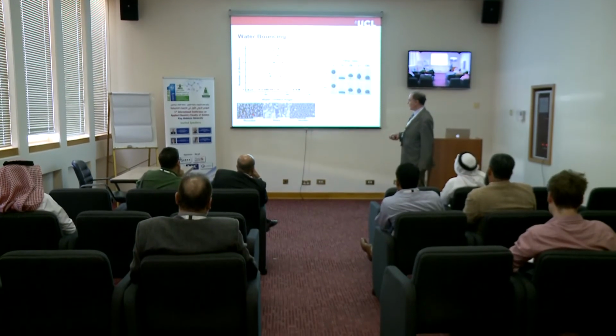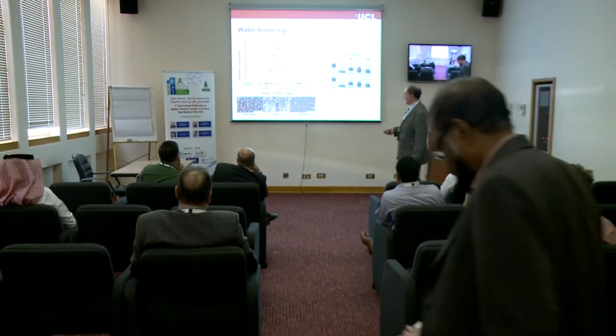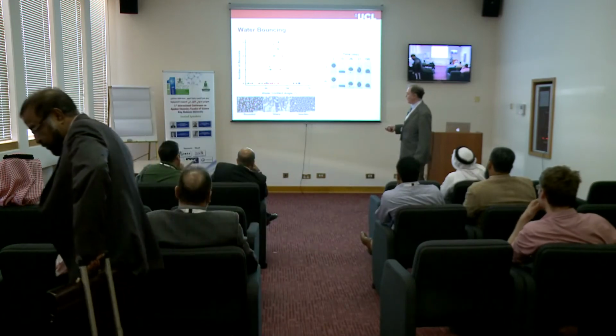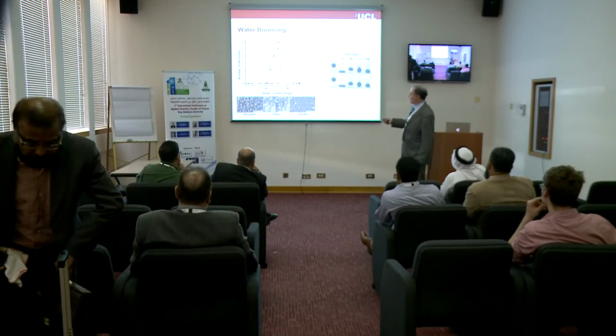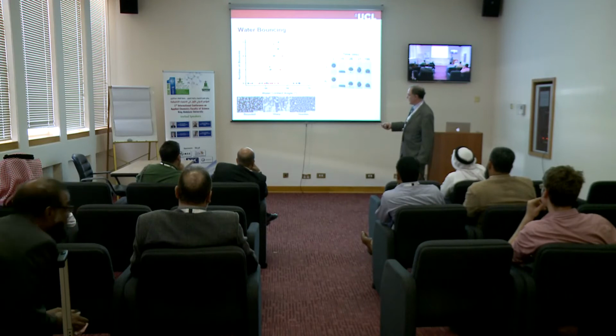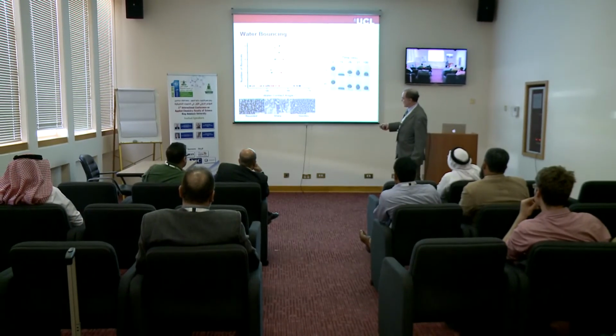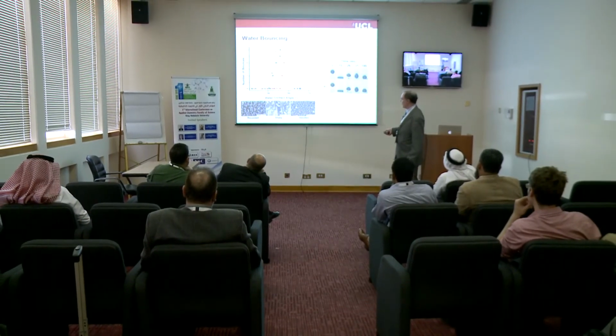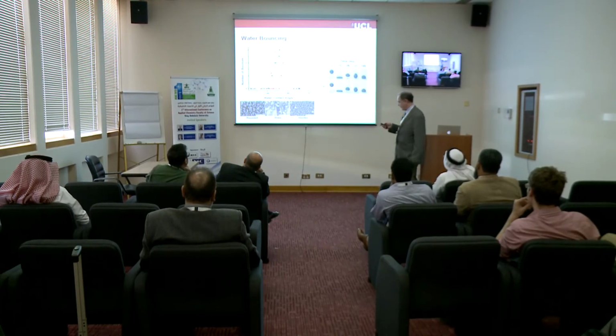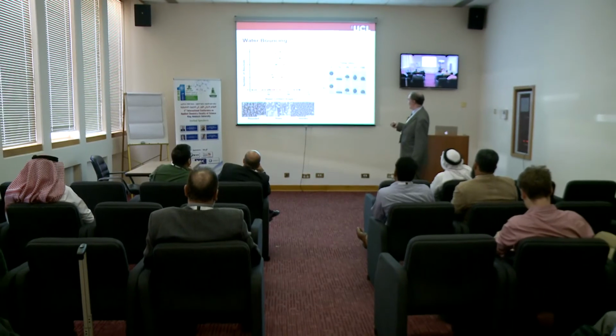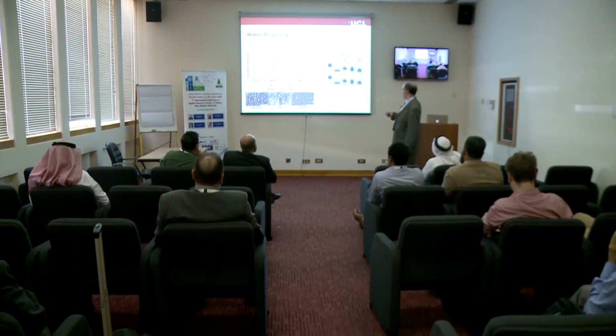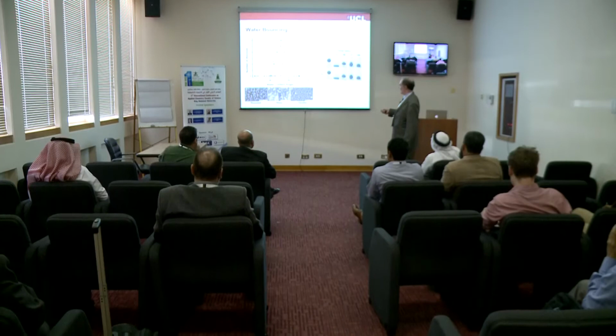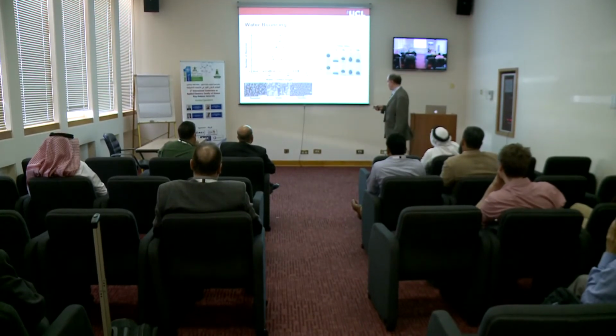We also found that the surface microstructure was important as well. If you have a rounded microstructure, you start clicking into the bouncing at 150 degrees. If you have sharp microstructure, it starts clicking in about 155. And if you have needle-like microstructure, it starts clicking in about 167. And what I'm going to show now is a series of how water interacts with surfaces when you put water, dropping it onto a surface which is super hydrophobic.